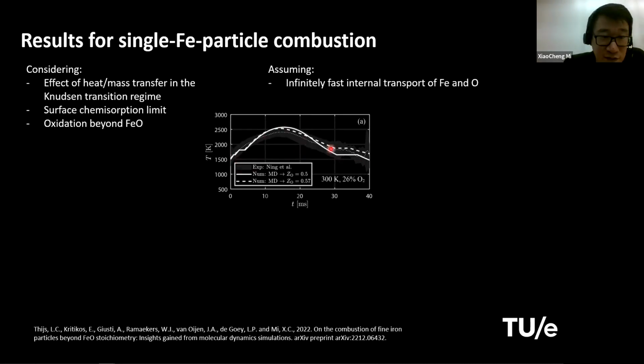And these are some results. The solid line is again the modeling results, and this small dotted line is the experimental result with the error bar, which is the shaded region. You can see again for this relatively low oxygen concentration, it matches very well, and we do not see that sharp pointy peak temperature anymore. You have a smoother transition from temperature increase to temperature decrease, and the cooling part seems to match the experimental result better, because in this case we do not have an inert cooling anymore. We have this further oxidation towards a higher oxidized product, and also the heating seems to match the experimental result better.